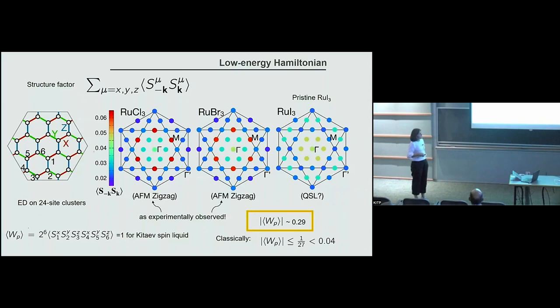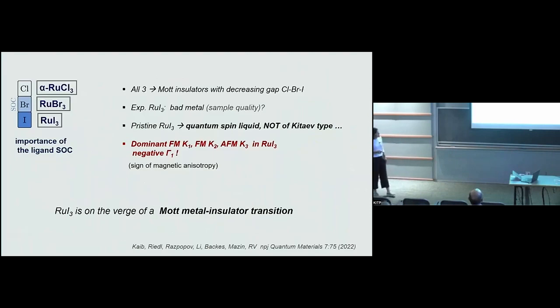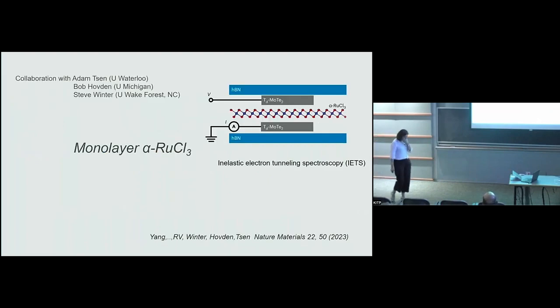Classically, this plaquette operator is 0.04. And for this type of model, it is about 0.29. So our conclusion is that if one were to have pristine ruthenium iodide, this would be a possible candidate of a quantum spin liquid, but not of a Kitaev type, due to these long-range interactions. And what is even more interesting is that this system is on the verge of a Mott metal-insulator transition. So the question is whether one can play with this metal-insulator transition depending on the sample quality, or by modifying the system. So that means that there is still a lot to be done in these hexagonal materials.